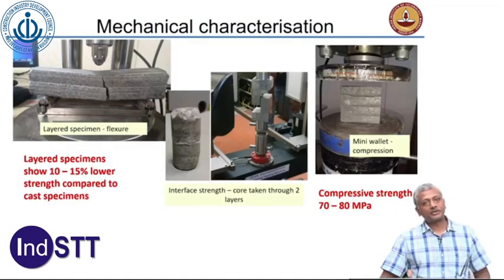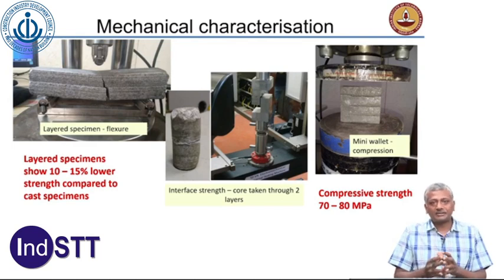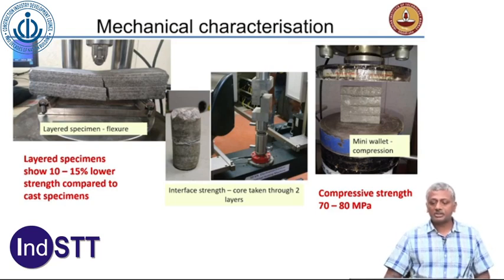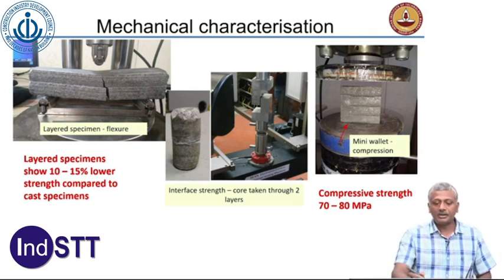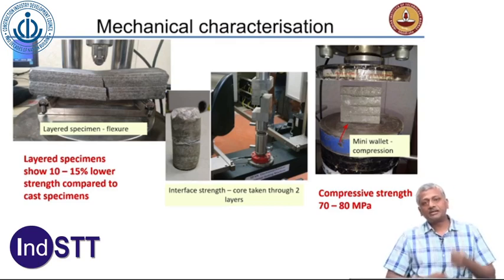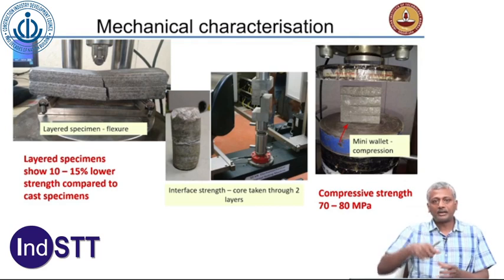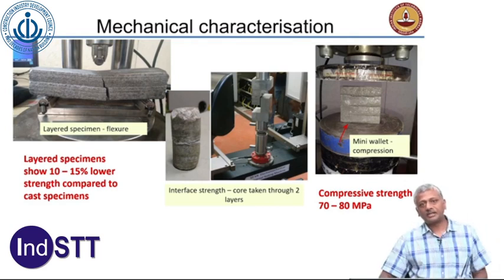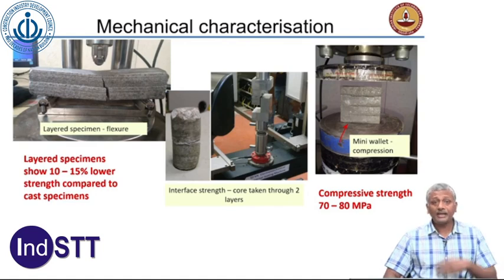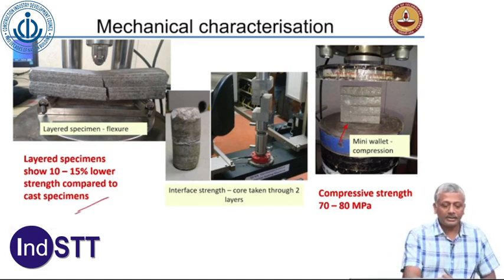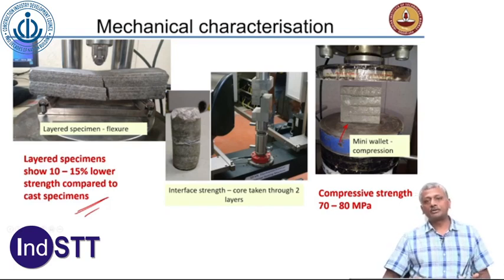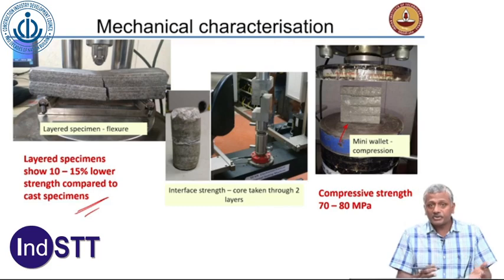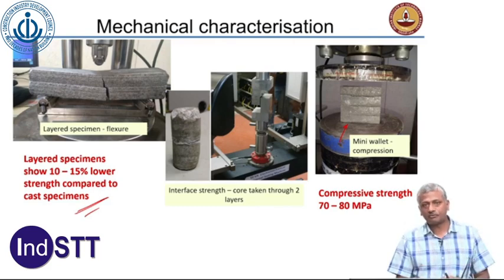Mechanical characterization can be tricky because you obviously can't really mold this material and then test it. So you have to test the strength of the material in the layered fashion itself. You can test the strength with respect to flexure, with respect to compression as a wallet for instance, or you also have to test the strength of the interface between layers, and that can be done by actually coring and then slicing or shearing the material across the layer. And the layered specimens were seen to have about 10 to 15% lower strength than compacted molded specimens. So that means that the layering does have an effect on the load carrying ability of these materials. How much of an effect? It's only about 10 to 15%, so that can be designed for without any difficulty.